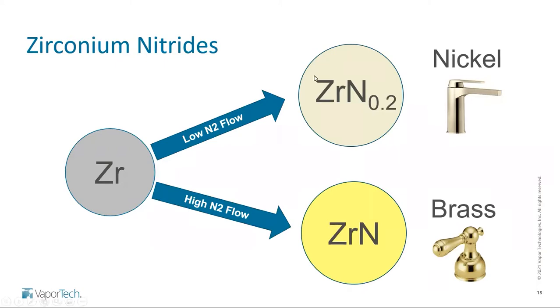It's still going to be much harder than pure zirconium. However, because it's not fully reacted, it doesn't have as much of the ceramic-like qualities, and it's not going to be quite as hard as something that's fully reacted, like a brass-colored zirconium nitride. Still going to have a lot of great properties, but just a little different. And we can change between these colors, and you can get anything in between just by modulating the amount of nitrogen that you're introducing in the chamber.